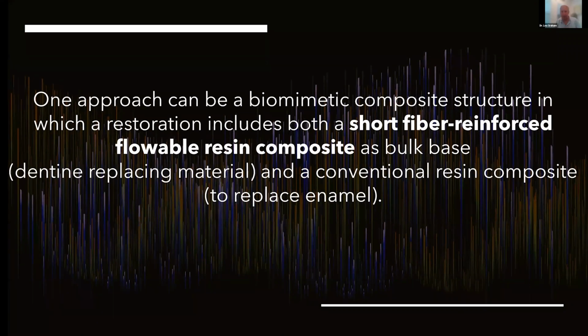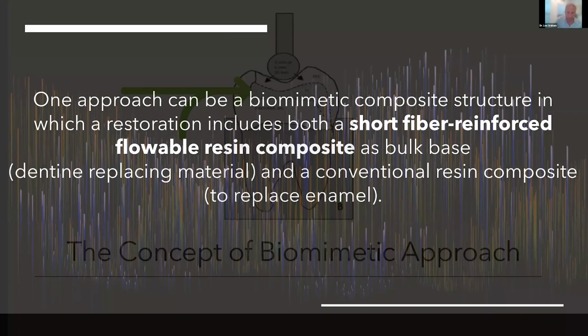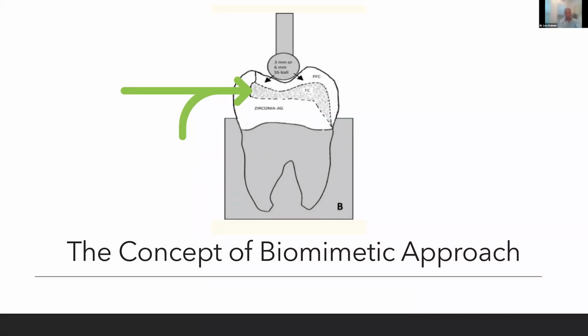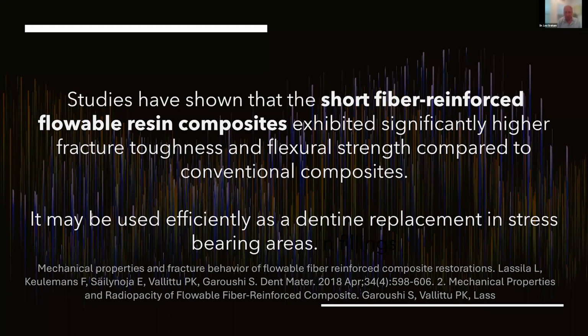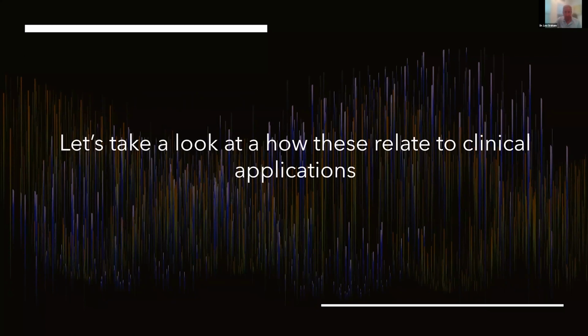So one approach is what we call a biomimetic approach. And in this case, it would be a biomimetic composite structure where you have the short fiber reinforced flowable resin as the base, and then your conventional resin composite to replace the enamel. So here's what it would look like. The concept of a biomimetic approach, as you can see the little fibers, they would rebuild the dentin, and then you would place a composite over the top of these in a biomimetic direct approach. So studies have shown, obviously, higher fracture toughness and higher flexural strength. Ideal. So what I want to do is, let's take this research and now apply it clinically.